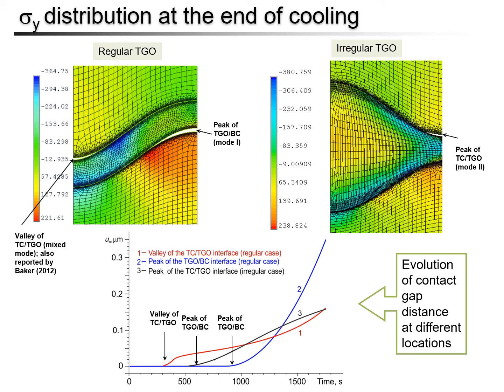Sure, the debonding leads to changes in the stress distribution in the TC and TGO layers, and this effect is more significant. For example, for irregular geometry of TGO, the minimum principal stress in this TGO layer increases in absolute value by more than 15% compared with simulation without considering the interfacial debonding.